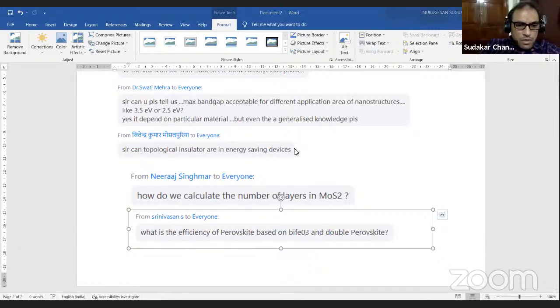What is the efficiency of perovskite-based solar cells, BiFeO3 and double perovskite? Okay, so for double perovskite, so far people have got close to 2% or something, but a lot of research is still going on. For the bismuth ferrite that we studied, we got 0.2%, which is of course 1/10 of that value. But there are composite-based molecular beam epitaxy or PLD grown films of some other bismuth ferrite compositions, and those were shown to exhibit up to 8% efficiency. The only thing is they did not do it on a large scale, and if we can show that on a large scale, that would be a very interesting and useful study.